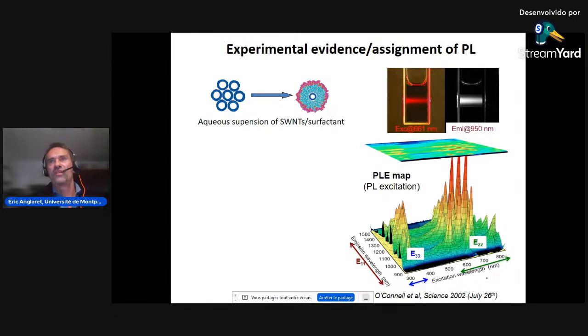And the first group who achieved it was the group of Weisman at Rice University in 2002, and they showed that to do that, you can use mechanical energy from sonication and then some surfactant to isolate the nanotubes and to prevent the reaggregation. And when you are able to do that, if you excite an aqueous suspension of single nanotubes stabilized by surfactants using visible light, you will be able to observe emission in the near infrared,